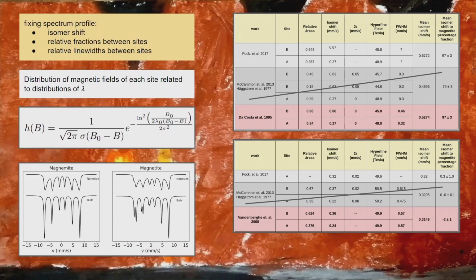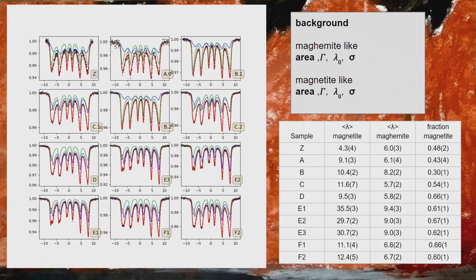So we have the parameters that are isomer shift, relative fractions from what the authors have measured in bulk samples, and also relative line width, because it's important to have the shape of the spectra. And we only will change the magnitude of the hyperfine field, only that. In that way, we fit all these spectra.